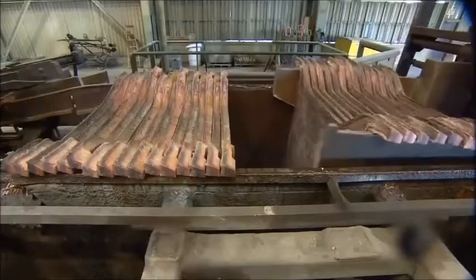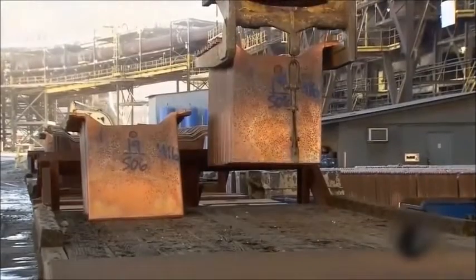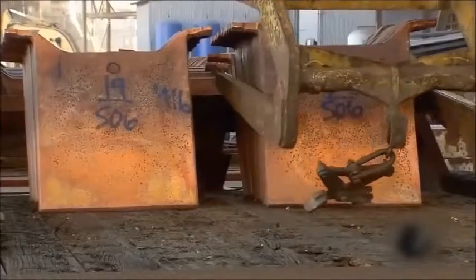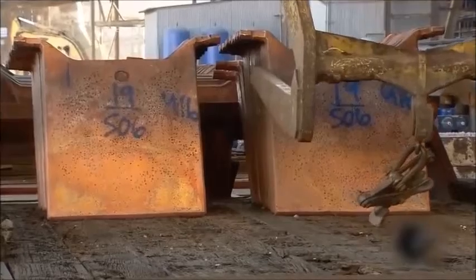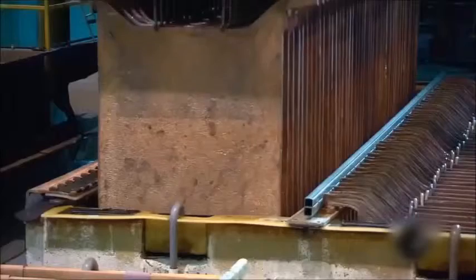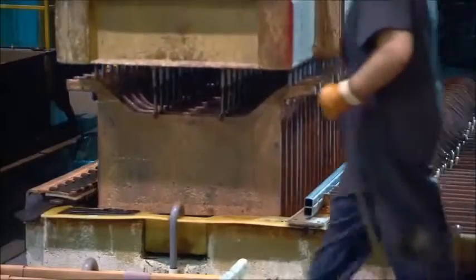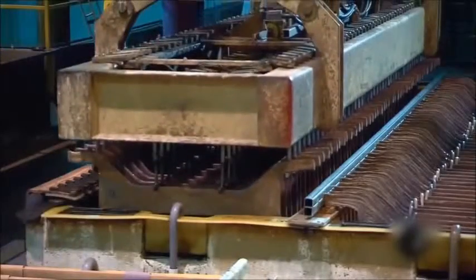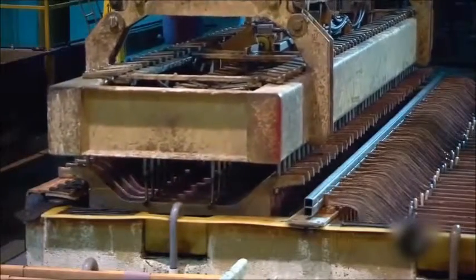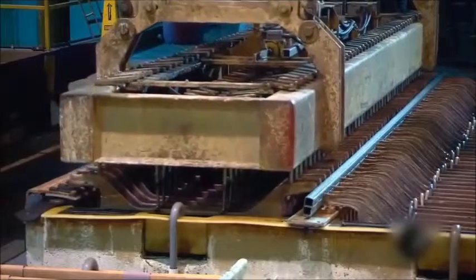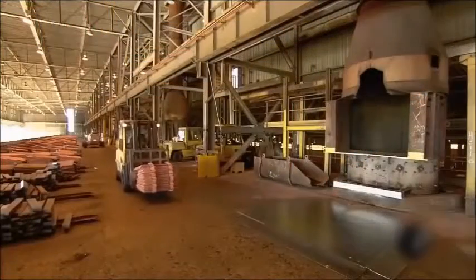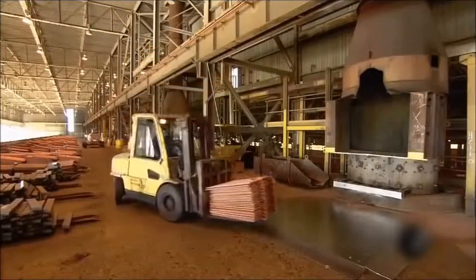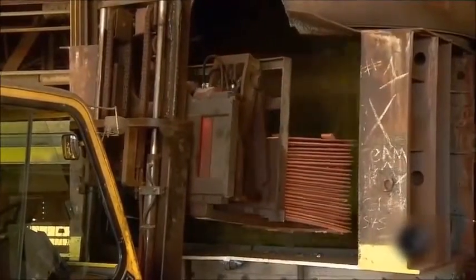Hooks formed during the molding make it easy to rack up the slabs for shipment to a Texas refinery hundreds of miles away. At the refinery, the copper slabs shed any lingering impurities in this tank as an electrical current is applied. The current causes the copper to gravitate to thin starter sheets. The impurities fall to the bottom. The copper deposited on the starter sheets is 99.99% pure, the purity level required by wire manufacturers.